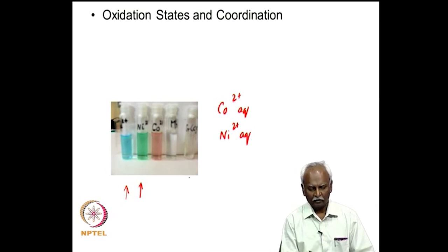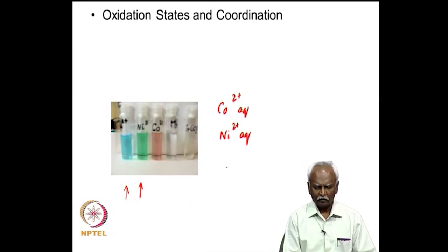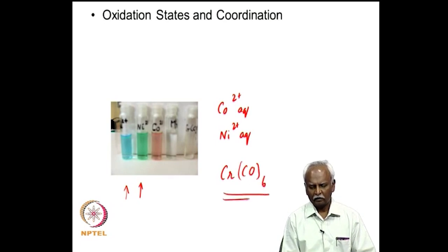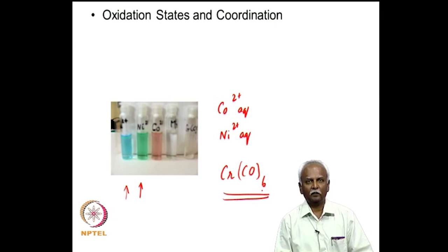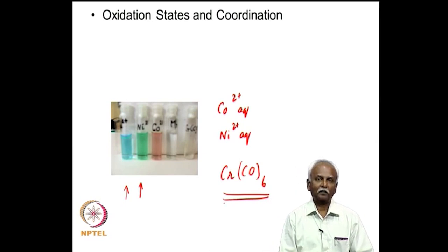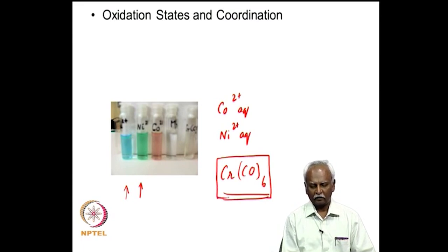On the other hand, if you take a chromium carbonyl complex, which we just talked about, CrCO6, this is neutral. And it is also interesting to note that it is a colorless species. So, although the oxidation state is one of the differences, it's also interesting that the color of these species tends to be completely colorless or at the most slightly colored yellow, in the case of iron carbonyl, like FeCO5 is light yellow in color. So, these complexes have a different color and they also have different oxidation states compared to classical coordination chemistry.